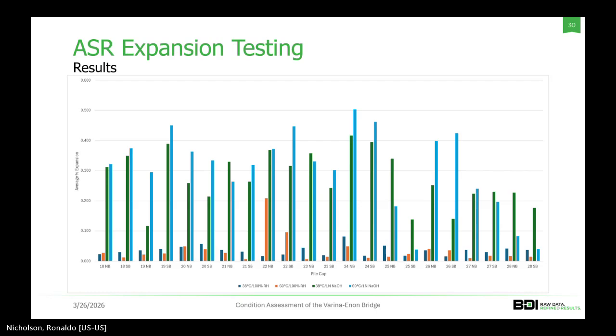These are some of the results of the 4 different combinations of the ASR expansion testing. In general, we perform some of the accelerated tests primarily to start collecting data in a shorter period of time versus the long-term testing, which does take about a year. As you can see, though, the 60 degrees C and sodium hydroxide solution, in general, the sodium hydroxide solution for both resulted in extensive average percent expansion.